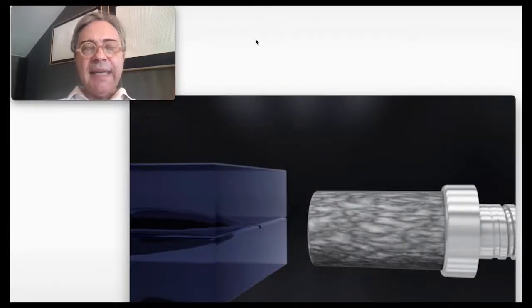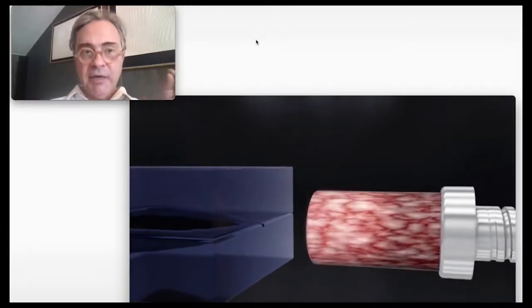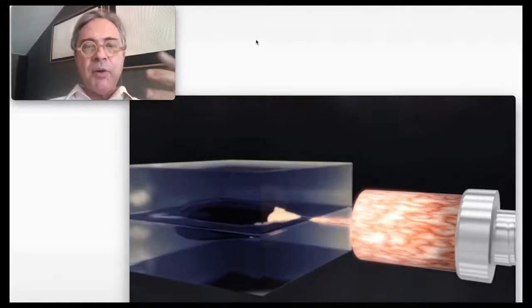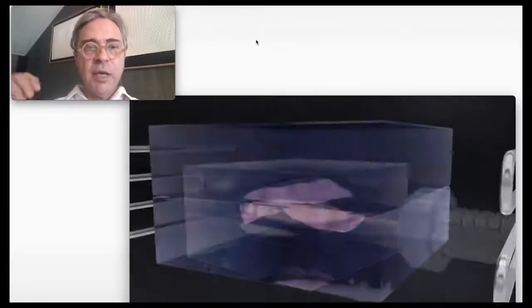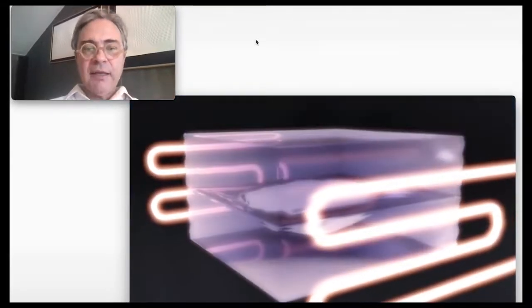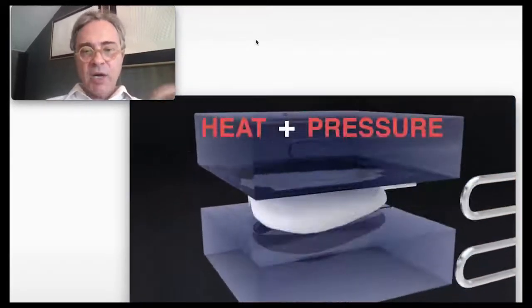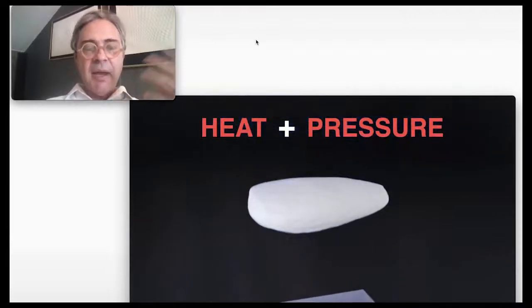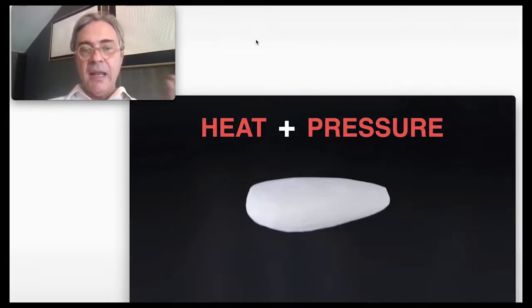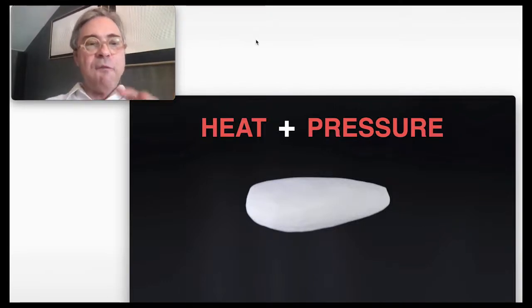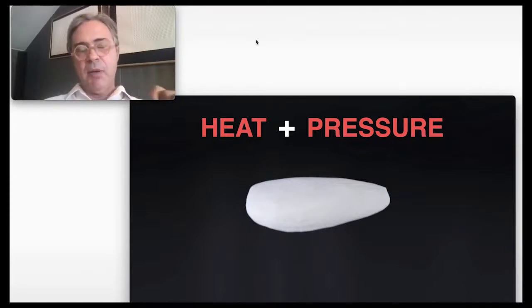And first, the ingot is heated at 300 degrees. And when composite reaches temperature, it becomes very, very fluid. And now it's pressed into the mold under 100 bars pressure and finally cured. So it's a heat and pressure process. And as a matter of fact, a lot of heat and a lot of pressure. And the addition of heat increases monomer conversion. So this is a fully polymerized composite, stronger and more color stable.